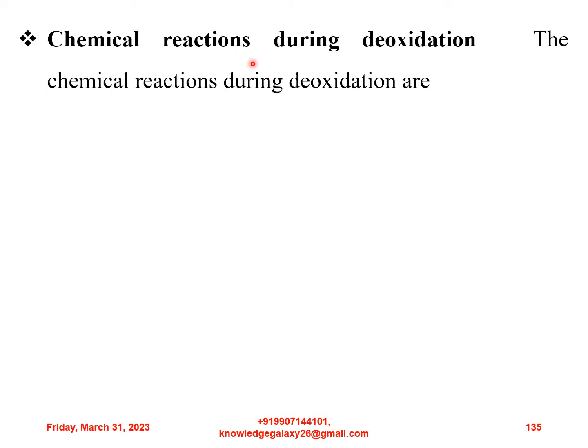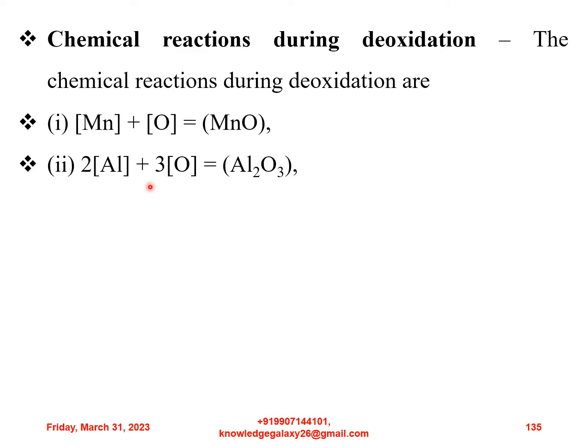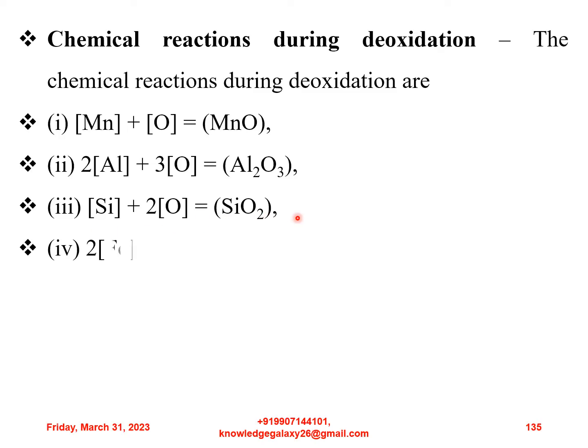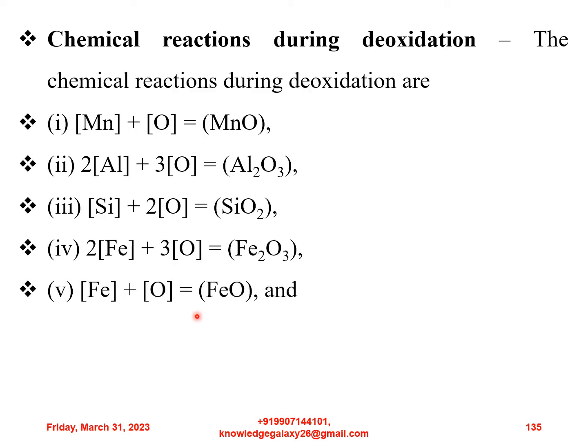Next is chemical reactions during deoxidation. The chemical reactions during deoxidation are: first, Mn plus O, this gives MnO. 2Al plus 3O, this gives Al2O3. Si plus 2O, this gives SiO2. 2Fe plus 3O, this gives Fe2O3. Fe plus O, this gives FeO, and C plus O, this gives CO.